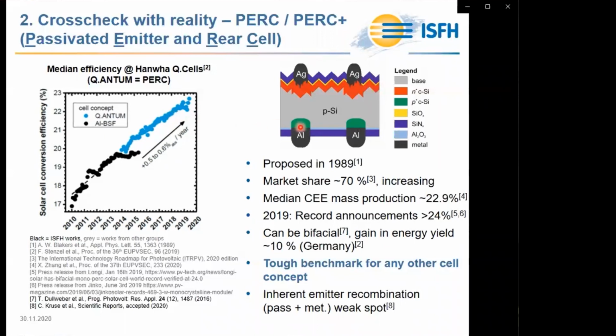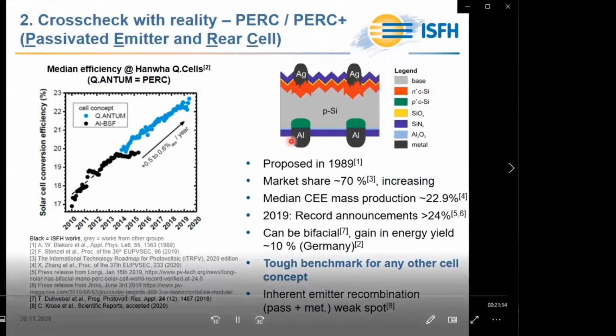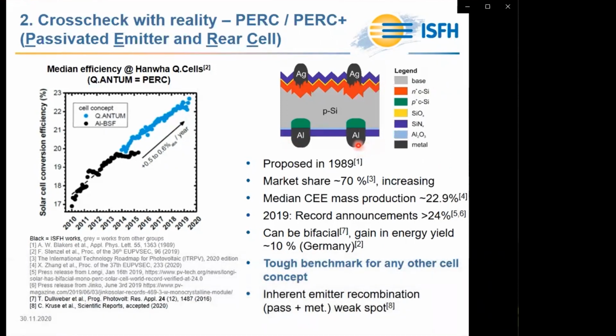It's worth to mention that a PERC cell can become bifacial by not printing the aluminum on the entire rear, but rather printing aluminum fingers. We call this concept PERC+. And by this bifaciality, you can gain an additional energy yield of around 10% on an annual average at the latitude of Germany. And of course, the benefit will be even higher in more sunny regions.